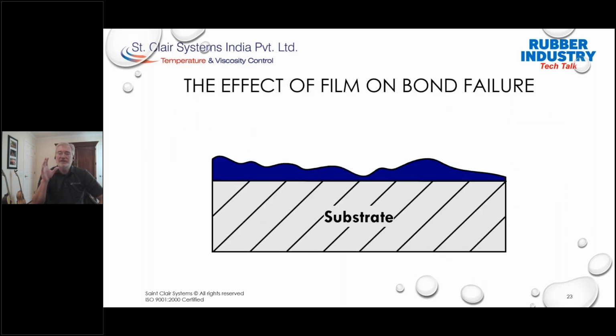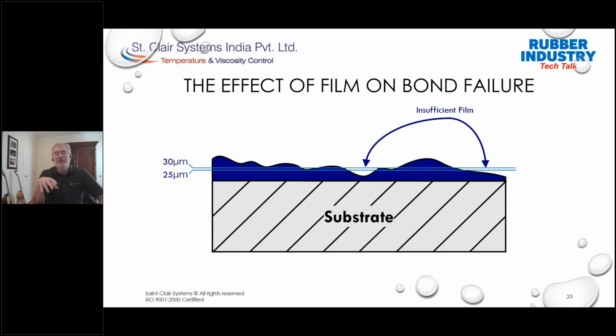So let's return to our film build example here, and we can see that we have a film thickness range between 25 and 30 microns, okay? And the areas below that 25 microns, as shown here, will have insufficient film. And it's hard for our rubber to actually get down into those cracks and crevices. So it creates a bonding issue, okay? This is our interlayer bond issue.